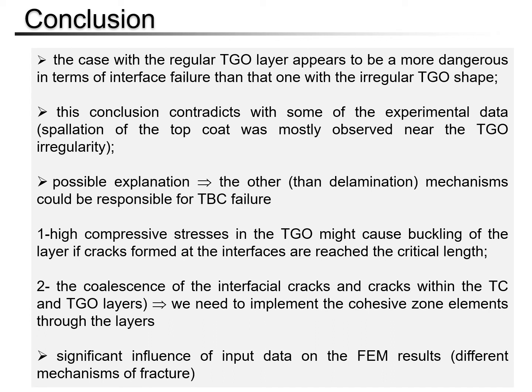And to conclude, the case with the regular TGO layer appears to be more dangerous in terms of interfacial failure than that one with the irregular TGO shape. This conclusion contradicts some of the experimental data. Spallation of the top coat was mostly observed near the TGO irregularity, so we were really surprised.